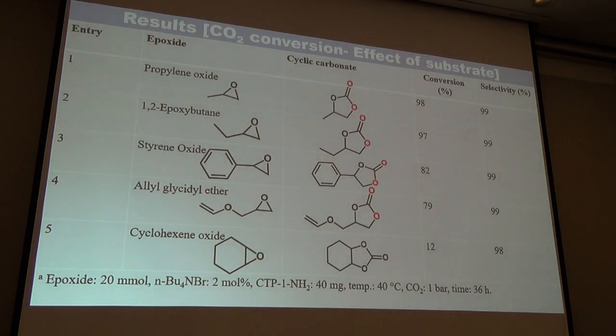And further, in order to check the scope of the catalyst, we have tested the cyclic carbonate synthesis using different epoxides, both terminal epoxides as well as internal epoxides. So we can see here all the terminal epoxides yielded a good conversion with high selectivity. Only the internal epoxide such as cyclohexene oxide shows a lower conversion. That is because of its high steric hindrance at this carbon position.